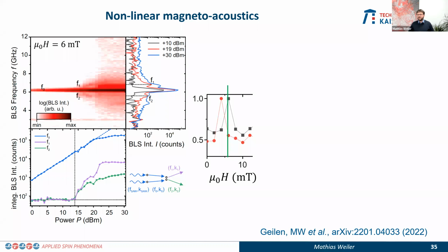Now we look at that a bit closer. We set the external magnetic field to 6 millitesla, which corresponds to the peak in the low driving power regime. And then we sweep the microwave power at this external magnetic field. What one sees is, first of all, at low powers, there's only one frequency. But then eventually, if one increases the power, other resonance frequencies appear. It's difficult to see on the color code, and that's why we have integrated the intensity at these frequencies. You can see there's a very clear threshold of about 15 dBm of microwave power, where we obtain additional resonance frequencies. And they can be explained as a confluence process of two phonons that then generate two magnons under conservation of frequency and momentum.